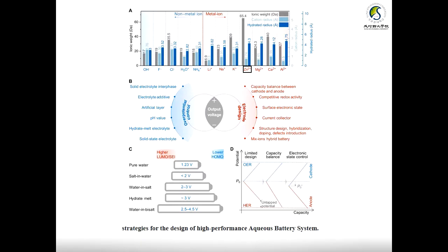The strategies for the design of high performance aqueous batteries: when compared to the pure water electrolyte, which provides around 1.2 volt, salt-in-water gives around 2 volt. In hydrated melt it gives 3 volt, and in water-in-bisalt 2.5 to 4.5 volt. It is dramatically increased when compared to the pure water.